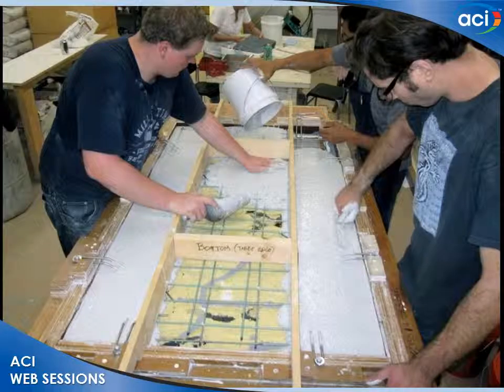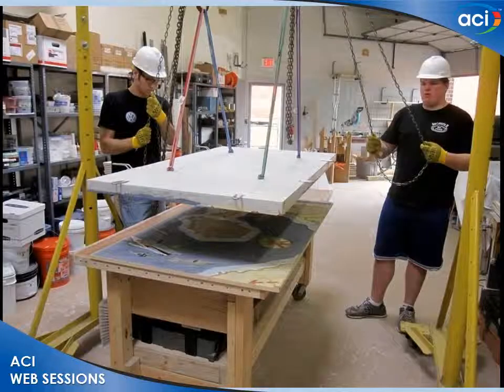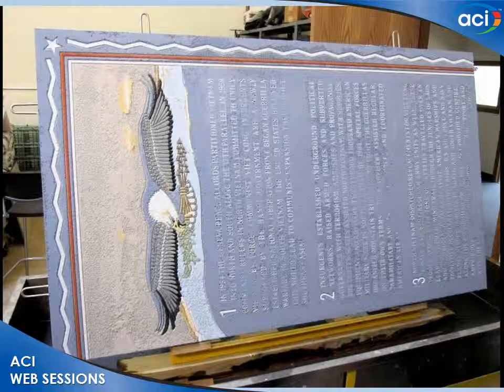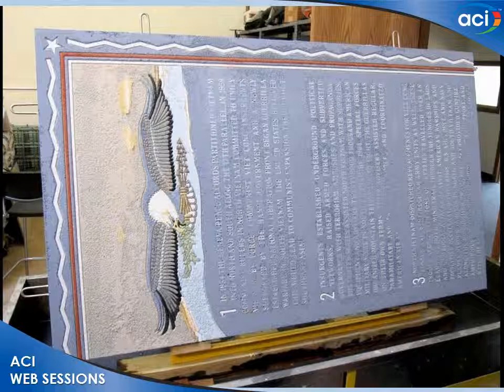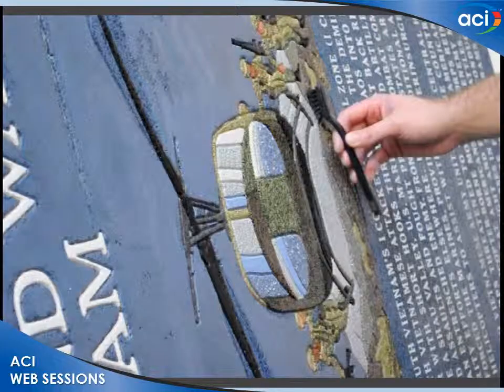We used a very similar backup mix, but instead of glass, we used a granite aggregate. But very similar properties, because we didn't want thermal differences. The next day, we removed it from the mold and set it up, this time on a steel frame instead of a timber frame. And this is how it looked before exposing started.